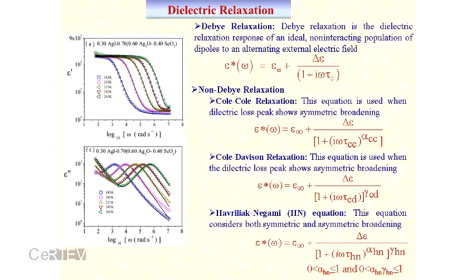Lastly, I would like to show you the relaxation of the charge carriers in glassy materials. I have considered this glass system, that is a selenium system. It has a glass former, a modifier, and a salt. I have shown here a representative dielectric spectrum as a function of frequency. At the high frequency region it is almost constant, but as the frequency becomes low, you can see there is a drastic change in this region.